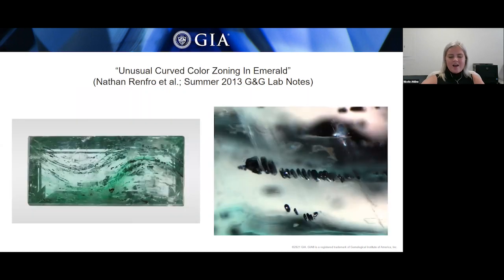Okay, so this emerald weighed a little bit over 1 carat, and it was obtained for GIA's permanent reference collection. When it was being examined for documentation, you can see this unusual curved zoning was noted. Gemological properties, again, were consistent with emerald. It had an RI of 1.589 to 1.597. It did have natural emerald inclusions that were pyrite and reflective thin films.